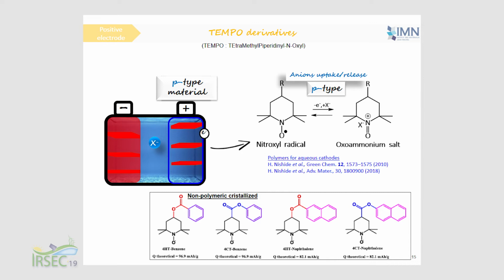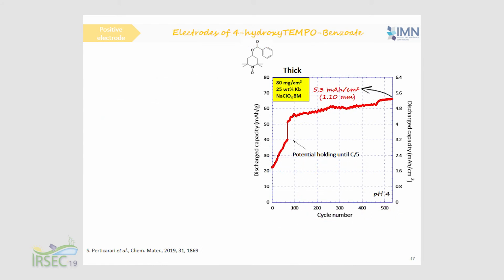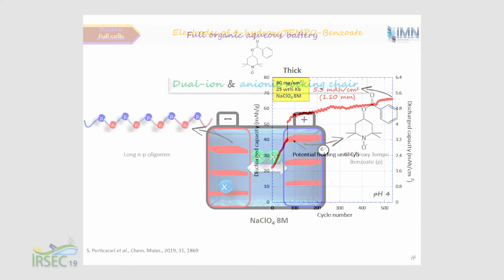So for the positive electrode, we have looked at TEMPO organic molecules. TEMPO-based polymers have been proposed by Nishide as a positive electrode for aqueous batteries, and in our case, we focus on non-polymeric materials. We focus on small organic crystallized materials. So we have tried many different molecules, and we find that this one gives the best result. And it gives the best result, for instance, for thick electrodes. Here we have 80 milligram per centimeter square, very thick electrode, more than 1 millimeter thick. You can see that we have good cyclability, and at 500 cycles, we still have more than 5 milliampere hour per centimeter square. This is what we expected.